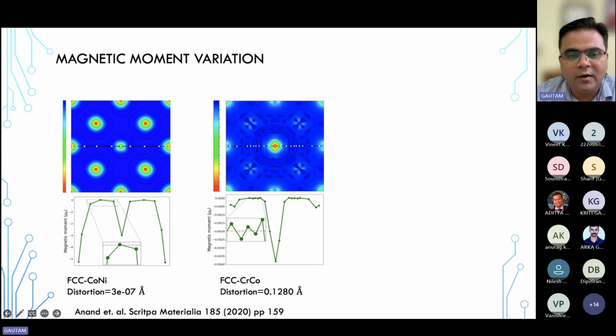But in the context of the chromium matrix with the cobalt impurity, as you can see, there is a fluctuation in the magnetic moment. The magnetic moment is significantly changing as you move from one end to another. So this was very interesting. Spin fluctuation is taking place, which might be leading to some kind of magnetovolume contraction.